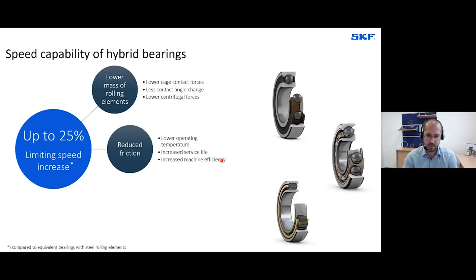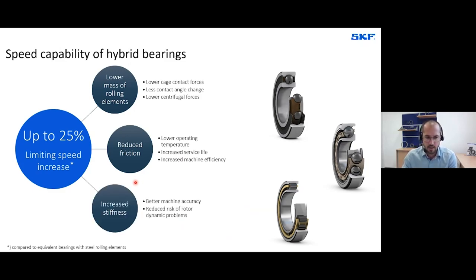The second effect, which is beneficial for the speed behavior, is the reduced friction. Reduced friction means lower operating temperature, especially at high speeds. Lower operating temperature means increased service life, you know, increased grease life, for example, and it helps to increase your overall machine efficiency. And another effect, which is at least as important, is the increased stiffness of hybrid bearings. If you have an increased bearing stiffness, it allows you to better control your machine accuracy, but it is also helping to reduce any risk of rotor dynamic issues or rotor dynamic problems.